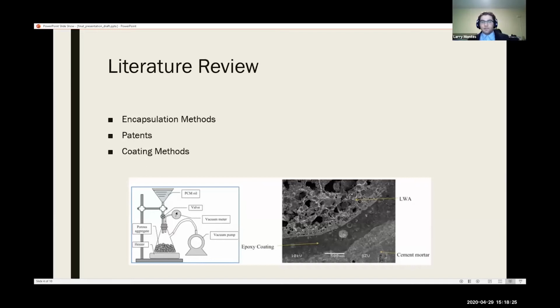For the literature review, we first look at PCMs that we possessed and whether or not they had a phase change around room temperature. And then we looked at various papers by other institutions to research methods for experimentation and implementing PCMs into concrete. The best method was by encapsulating the PCMs within porous aggregates that would be inside the concrete. Other methods, for example, simply mixing the PCM into the concrete mixture, led to cracking within the concrete after the PCM changed phase. We then looked at patents that may be similar to our project.